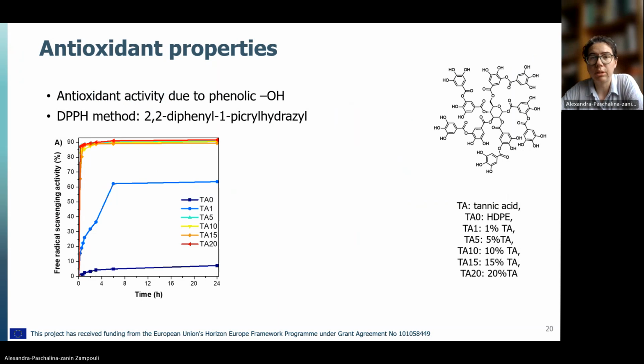Now, when it comes to the antioxidant properties, which was the main focus of this study, they were assessed by the DPPH method. The DPPH method is based on the 2,2-diphenyl-1-picrylhydrazyl radical, which is a stable radical under ambient conditions. In a solution, it gives a nice purple color, and it absorbs at around 517 nanometers. In the presence of antioxidant compounds, the radical is scavenged, and therefore the absorbance decreases. So by measuring the absorbance, we can calculate the radical scavenging activity of our composites.